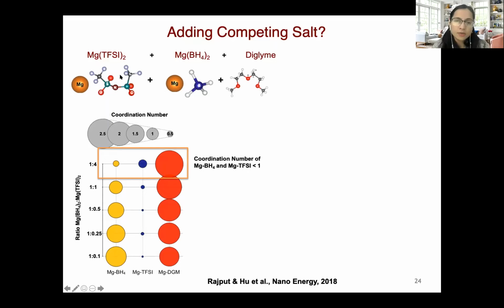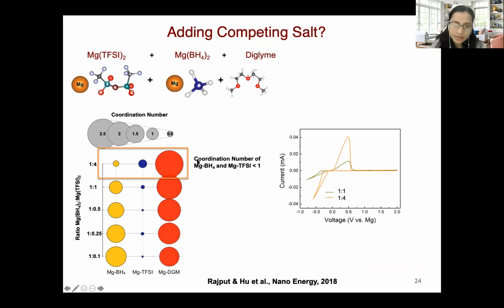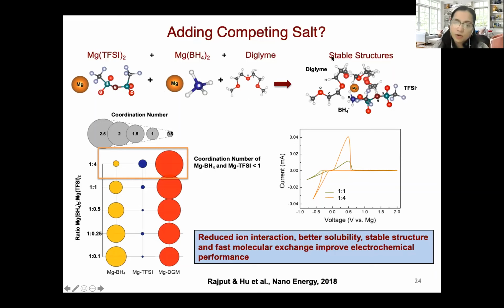And in this competition of TFSI and borohydride anion to bind with magnesium, it's actually the solvent who wins, and the coordination of magnesium and solvent increases. And our experimental collaborator tested this, and they found that indeed at this particular ratio, the electrochemical performance is the best. And we identified that we are forming several stable structures in the solution, where we have both the TFSI as well as the borohydride anion in the first solvation shell in such a way that it increases the stability of the anions as well as the solvent molecule.